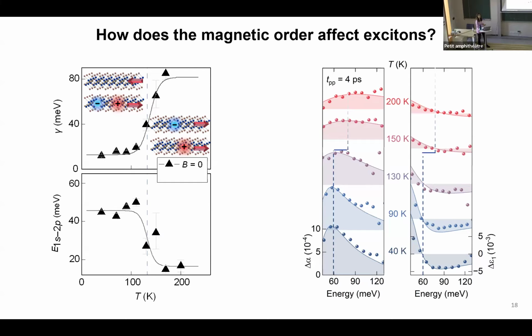Let's interpret them one by one. What we see is that the 1s2p transition energy drastically reduces across the Néel temperature. Why is this happening? Because the electron and hole pairs are more delocalized across space, so they are less bound to each other. So the binding energy drops.